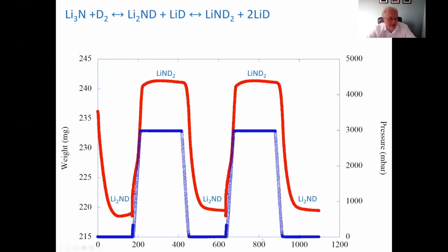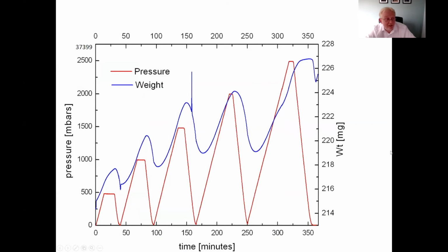But you can also look at the dynamics as well. You can think about what happens to the cycling of this process. Here we've applied the same pressure over the same time scale at the same temperature, and we've got the same behavior in each case. We've gone to lithium amide in both cases, and then when we remove the pressure, it goes to lithium imide, and all these reach the same sort of level. So it's a very repeatable process. We can also try and vary the pressure.